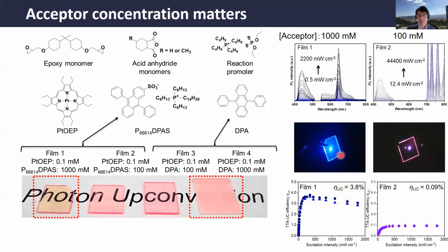With this rigid film, we shone the green laser, and we observed nice green to blue upconversion in air, and the efficiency is quite good, 3.8%. But when we reduce the acceptor concentration from 1,000 millimolar to 100 millimolar, the efficiency dramatically drops to 0.09%. We cut the phosphorescence by a short pass filter, but we still observed very strong phosphorescence. So the donor to acceptor triplet transfer is not efficient, and eventually the upconversion efficiency was very poor. So you need such a high concentration of acceptor, not only for triplet exciton diffusion between the acceptors, but also for the triplet transfer from donor to acceptor.